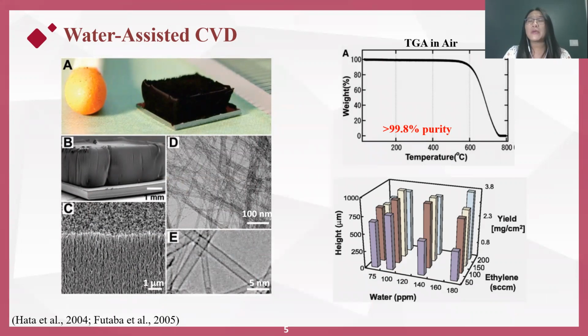They believed that the water vapor served as a weak oxidizer and selectively removed the amorphous carbon without actually damaging the CNT network. With a prolonged catalyst lifetime, this technique is anticipated to provide a simplified approach for achieving high purity CNT synthesis more efficiently. While the conventional substrate CVD process can tune the nanotube diameter by precisely controlling the catalyst sizes, the significant batch-to-batch variations remain a huge drawback for this process.